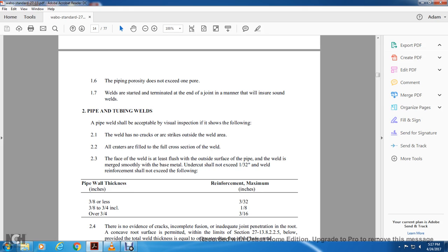The weld has no cracks or arc strikes outside of the welded area. All craters are filled to the full cross-section of the weld. The face of the weld is at least flush with the outside surface of the pipe. The weld merges smoothly with the base metal, and undercut should not exceed 1/32 of an inch. Weld reinforcement shall not exceed the following. Pipe wall thickness less than 3/8 of an inch: reinforcement 3/32 of an inch. Pipe wall thickness 3/8 of an inch to 3/4 of an inch: reinforcement maximum 1/8 of an inch. Over 3/4 of an inch: 3/16 of an inch.